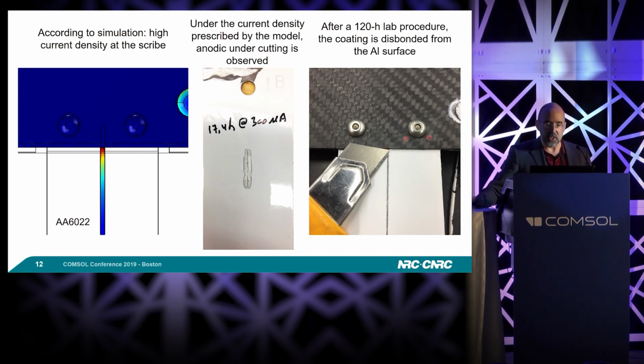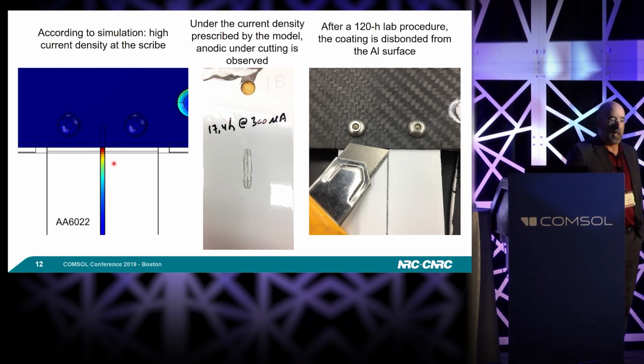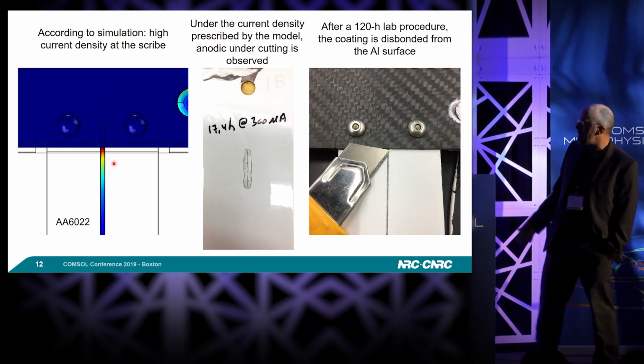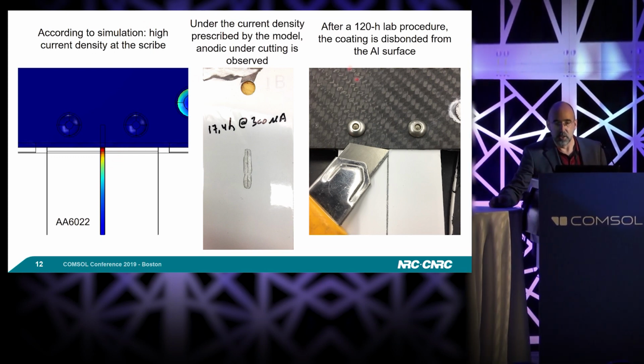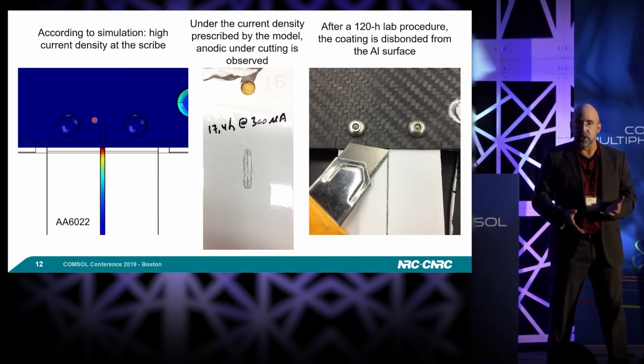With the high current density in the lab under polarization, it disbonded. Now, if we try to peel it after the lab exposure under a cycle, wetting, drying, we see that we can easily peel it. So the end of the story is that instead of going with a very long lab exposure like we've done here, we can simply run the model. It takes a few minutes.